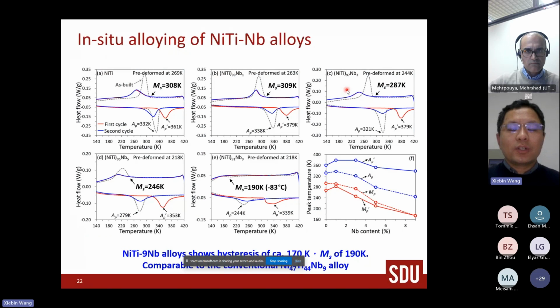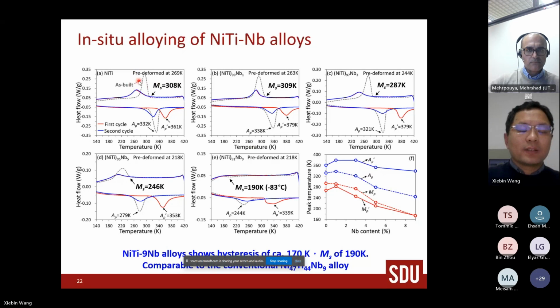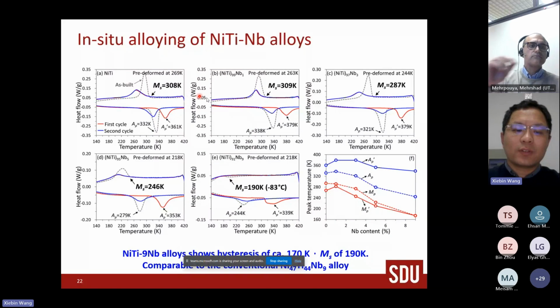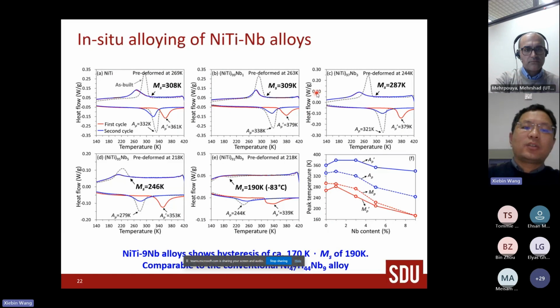And for nickel-titanium-niobium ternary alloys, the most important property is the transformation hysteresis. So it means the difference between the cooling peak and the heating peak. Normally we check not only the printed alloys but also the conventional alloys. We check the hysteresis. Firstly, do a pre-deformation and then heat it up to check the transformation temperature. Because, for example, if you look at this first figure.